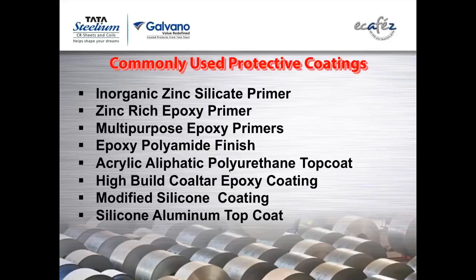The zinc by weight recommended by specification is 80% or in some cases 85%. But by weight, zinc has a very high specific gravity, so naturally the volume will not be so much in a liter of paint. Then there are some multi-purpose epoxy primers. So this multi-purpose can be indoor, outdoor conditions, or they will have zinc phosphate or some kind of inhibitive pigments in that. Then epoxy polyamides normally are used for high-end laminations or tank inside lining, say water tank inside lining or something like that.